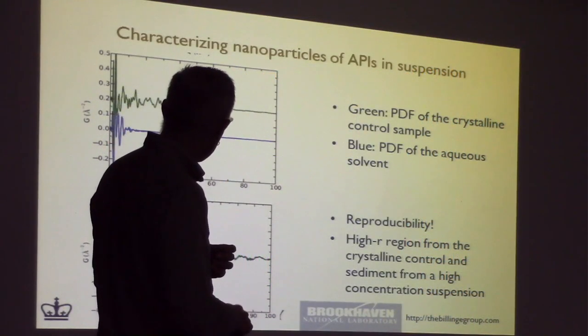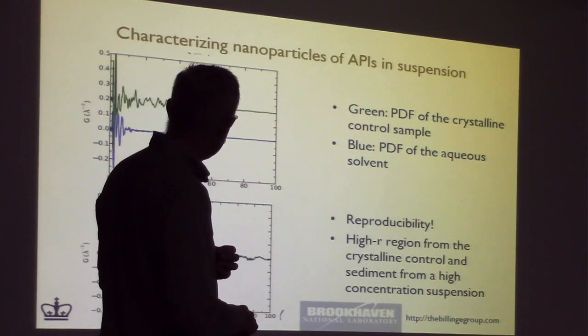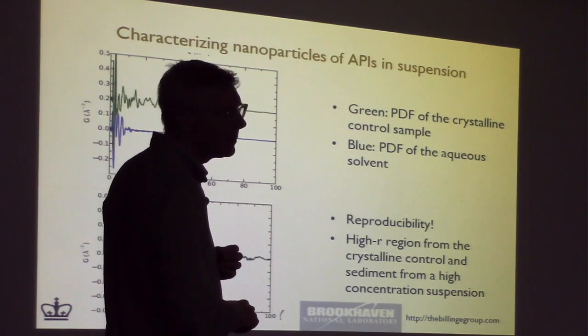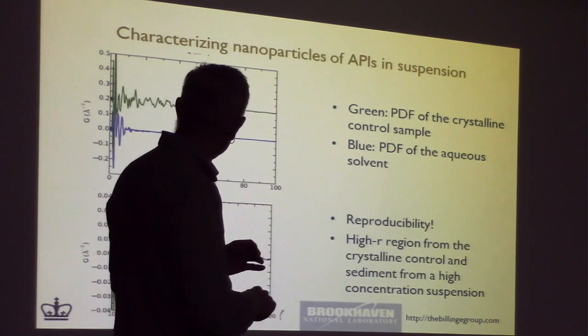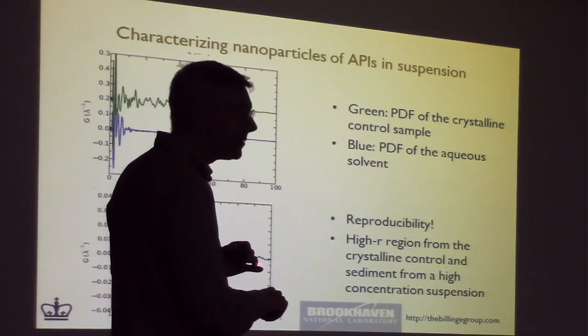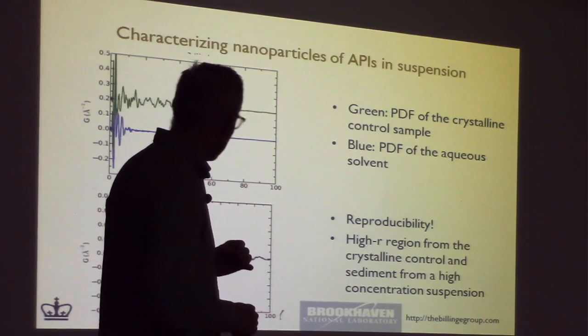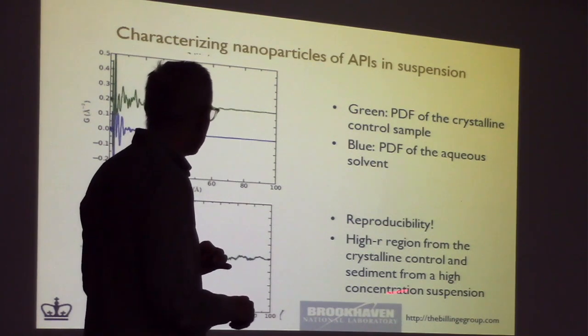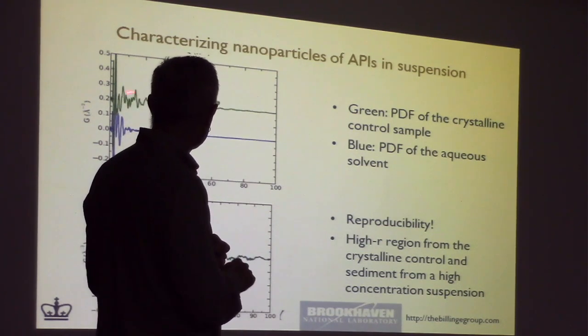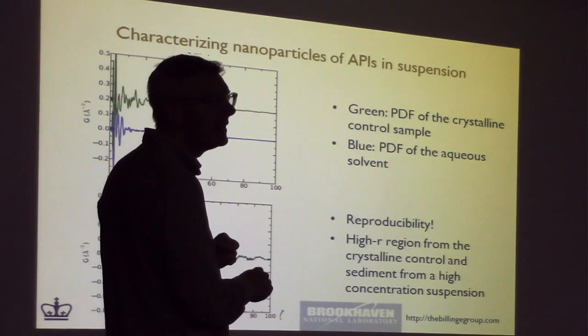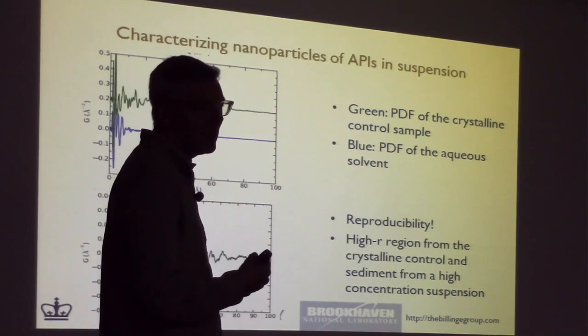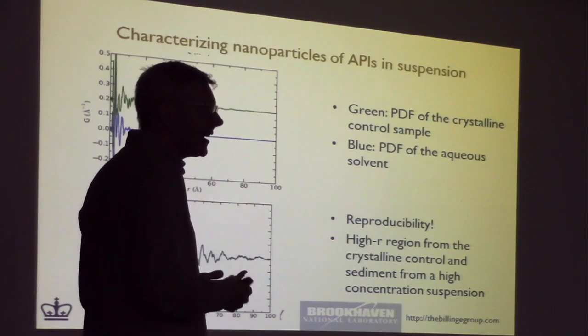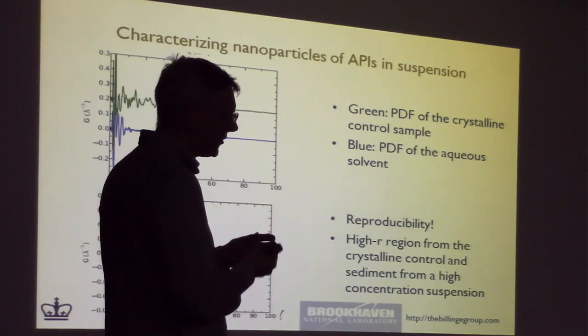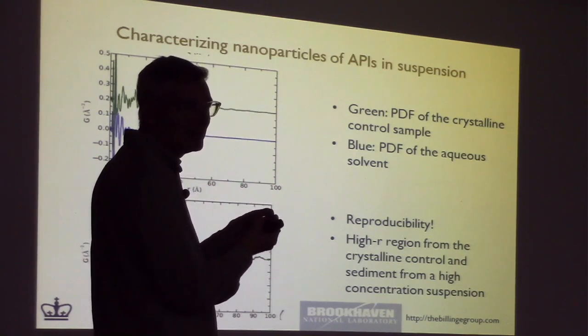Now, we get very high reproducibility. So what you can see is a green curve and a blue curve here, and even the tiny little ripples are reproduced, basically. And these come from, I don't remember which way around it is, but one of them is coming from the dry crystalline control sample we had. The other one is coming from the material that was precipitated out of solution.